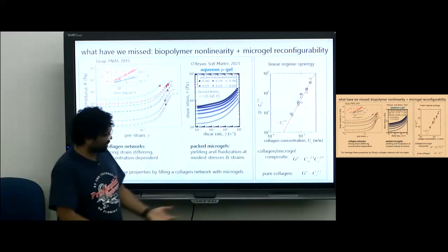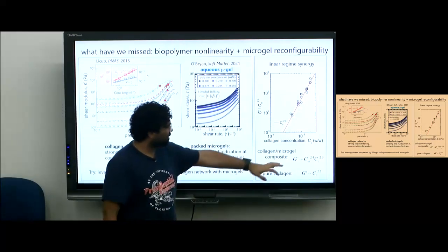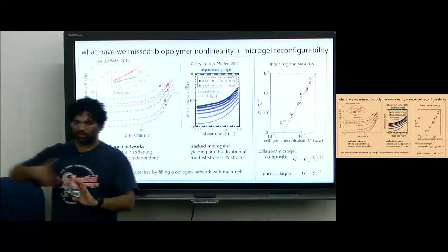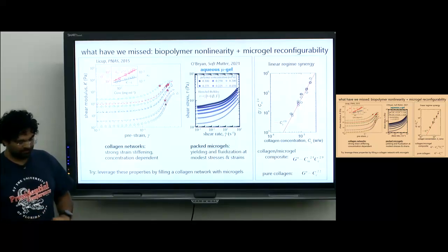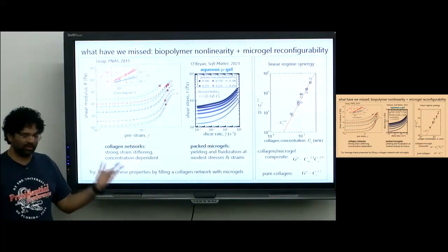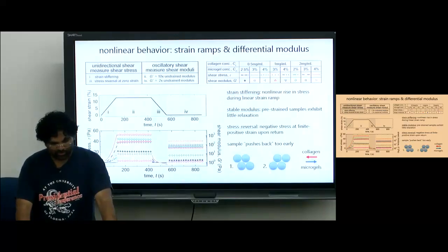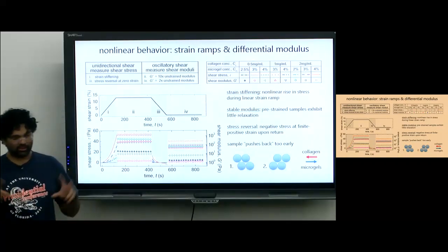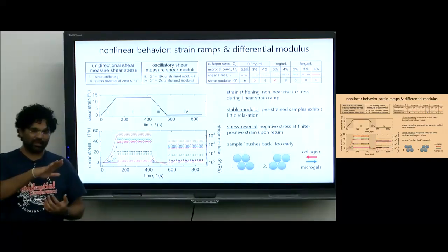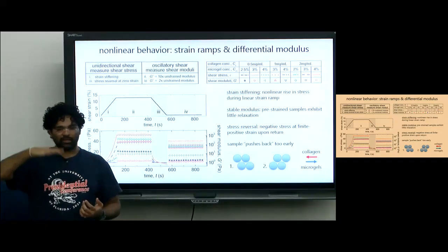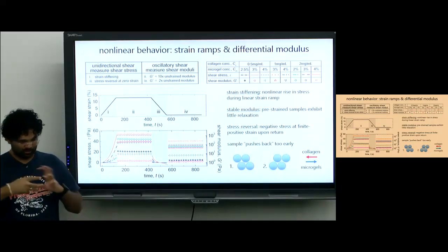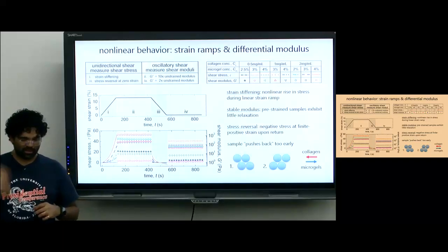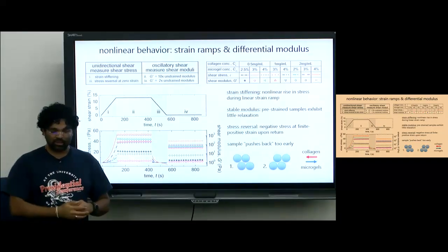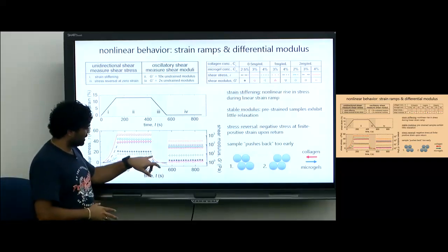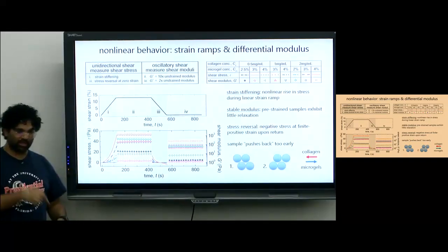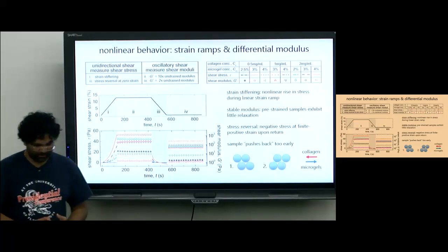we were able to do a bunch of rheology tests on these composite materials and figure out a relation for the storage modulus over the concentration of microgels and collagen. They strongly depend on collagen concentration and a little bit weaker on the microgel concentration. Then we also wanted to test how this nonlinear behavior would work. So we strained the sample, held it at a particular strain, and did oscillations at that pre-strained state to measure what the modulus would be, and then ramped the strain back down and again measured the modulus. When we did this, there was a really cool behavior where the stress reversed. The stress went in the other direction, which was really interesting to us.